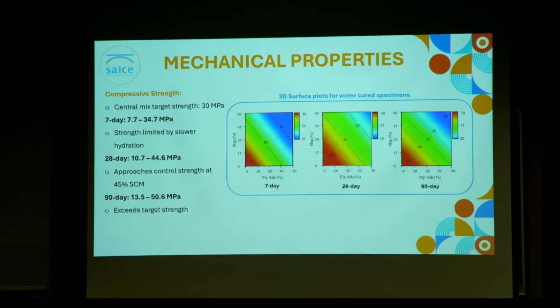Compressive strength was tested at 7, 28, and 90 days for both curing conditions, and linear models with coefficients of determination ranging from 0.89 to 0.98 were developed. All mixes exhibited low early age strength ranging from about 7 to 35 MPa, followed by a notable strength gain